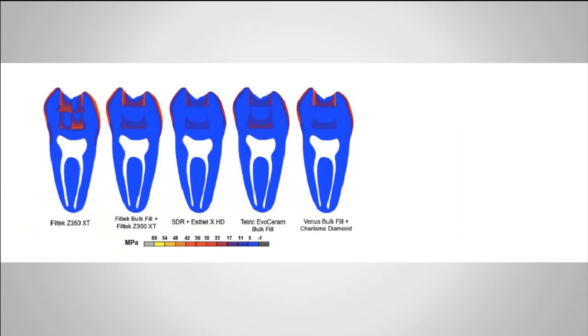If you see the images on the left side, using too many layers with a regular composite, sometimes you have more stress on the interface than using bulk fill composites. So the first idea for me of bulk filling a cavity is that I can have a very good result at this interface, without stress, using just one layer. This is the contrary of what I used to believe in the past.